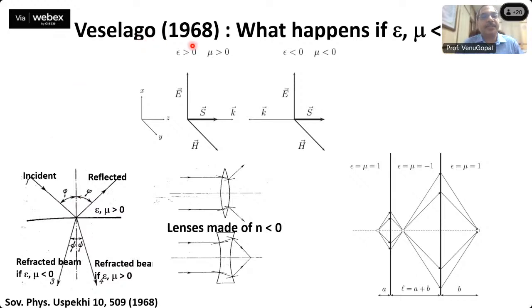So he did a small theoretical paper in which he considered the consequences of having epsilon and mu negative. The first thing he showed is that when epsilon and mu are positive, we have the right-handed triad, and the wave vector and the Poynting vector, the energy propagation, are both in the same direction. However, if epsilon is less than 0, mu is less than 0, and n is less than 0, the refractive index is negative, then E, H, and K form a left-handed triad. And in this case, the wave vector and the energy propagate in opposite directions.